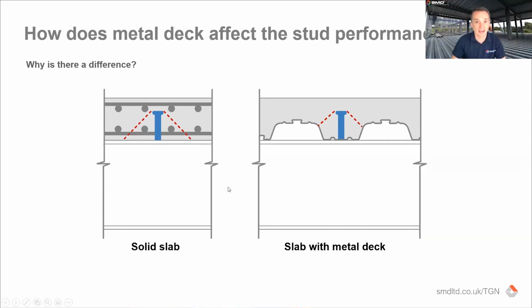So talking about how does metal deck affect the stud performance, and me mentioning there that it's very much in the concrete failure. As you can appreciate, if we have a solid slab, you would see something like this, the beam running left to right in these images. So in a solid slab, you have a cone that goes right the way down to the base, so you have a lot greater shear surface in the concrete than you do if you then have that within a deck, because obviously at certain points it will impact with the deck itself.